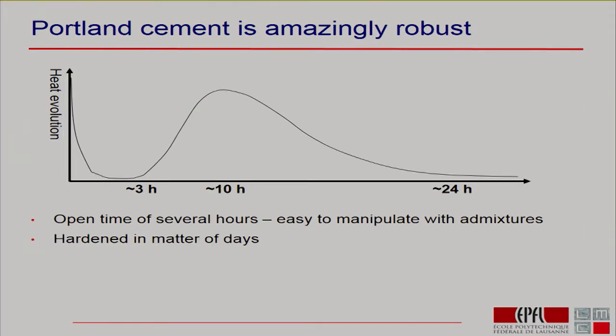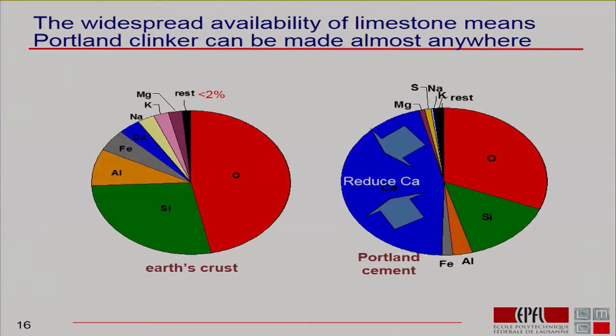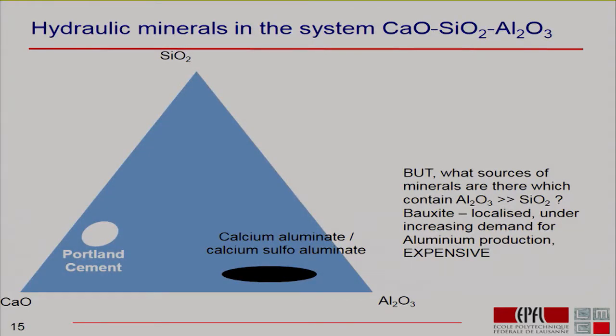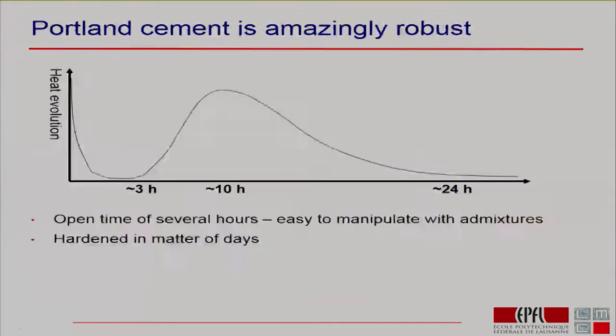And what we see is we get a very high heat evolution to start with, then it dies away, and it stays quite low for a period of 2 to 3 hours. This is very, very useful because it means you can mix the concrete, and then you can transport it, and you've got this period of a few hours where you can put it in place. And not many materials do that. I mean, the calcium aluminate or calcium sulfoaluminate systems we looked at here generally set much faster. And this is also robust. It means it can be used by almost anybody, almost anywhere.